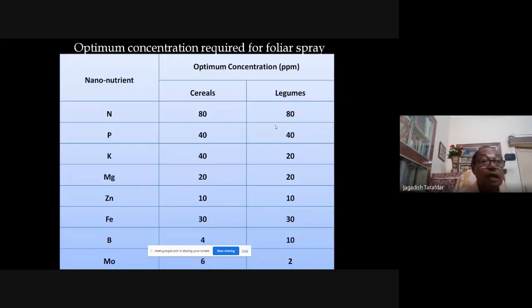Then you can see we have optimized the concentration for all types of crops, what concentration of nanoparticles we have used so that the plant does not get injured. That is also very important when you go for foliar spray. We found that for cereals, biosynthetic nanonutrients, nitrogen 80 ppm is the best. Legumes 80 ppm is the best. Phosphorus 40 is the safe limit. Potassium 40 ppm for cereal is the safe limit. Legumes 20 ppm is the safe limit.